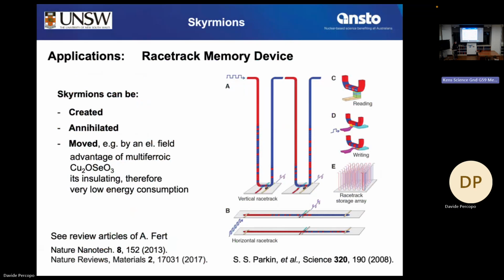Applications. Racetrack memory device. Now we can also create single isolated skyrmions and move them around. And each skyrmion is like a data bit. If they have a size of just 10 nanometers, that's a factor of 10 smaller than the domain walls in the current hard drive. And in the area, that's a factor of 100, 10 squared. Which means we can achieve much, much higher packing densities than on a hard drive.